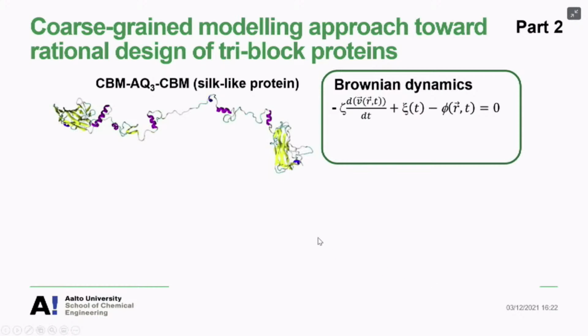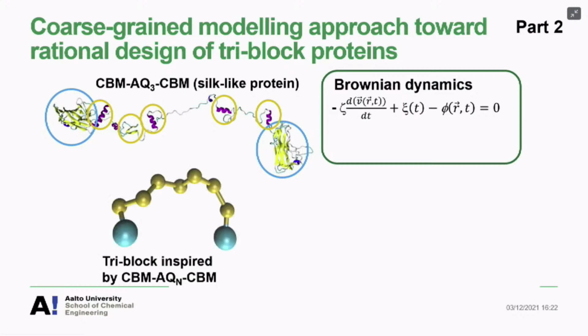So what I have here is the atomistic structure from the simulations that I showed, and then I'm coarse-graining it. I'm taking the end units and making them into big blobs. Then I'm looking at what else is there. I'm taking the stickers that were the alpha helices and the beta sheets in the flexible part. And this is intrinsically disordered. They are not always at the same place. There are sequences there that are more prone to alpha helix formation. I don't really know where they exactly are. I know the likelihoods of where they are going to show up and approximately how many there are.